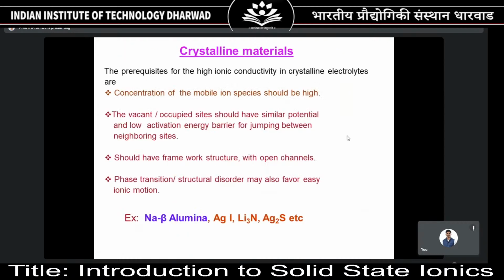Coming to each category, crystalline material, as I told, the concentration of mobile ion species will be high, and as I told in the previous slide, there will be vacancies or disorders. Based on that, the vacant ion will move from one side to another, and they don't need much activation energy. For example, the basic example is sodium beta alumina, which was commercialized and also used in high temperature sodium sulfur batteries. Silver iodide has been used in batteries in pacemakers and so forth. Lithium nitride and silver sulfide are classic examples of crystalline materials.